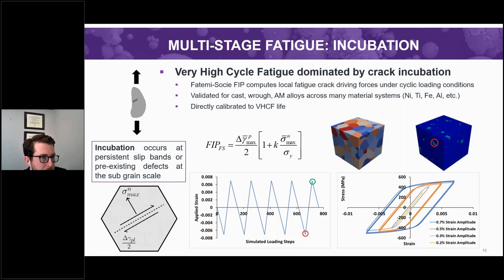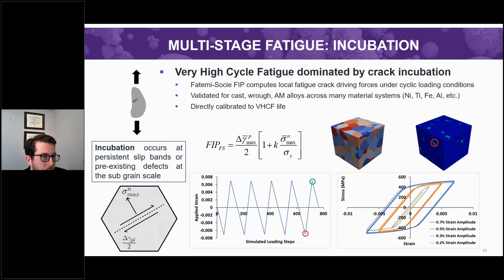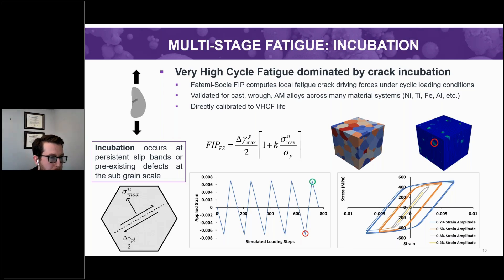At the sub-grain level, crack incubation can occur within one grain due to the accumulation of slip — in other words, dislocations in a crystal structure which move under loading. As the cyclic loading continues, they accumulate at areas where there are barriers to slip, like grain boundaries or defects like inclusions or pores. This is especially important when we are considering very high cycle fatigue. In the very high cycle fatigue regime, the vast majority of fatigue life is spent in the crack incubation stage.